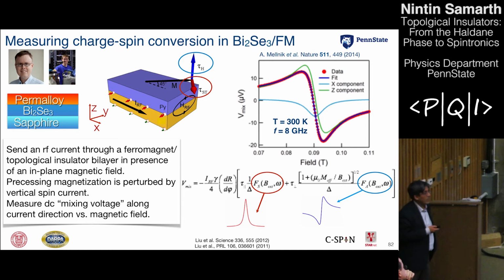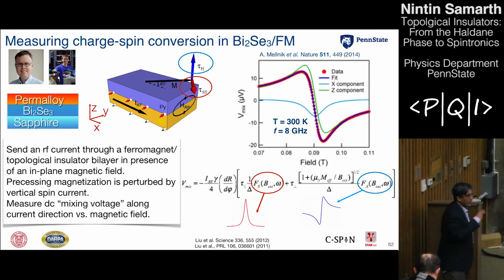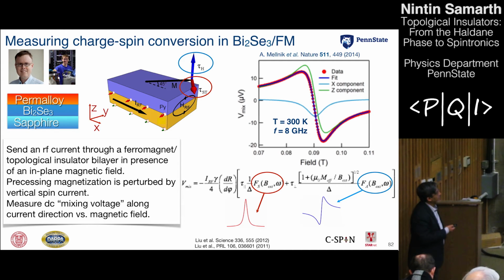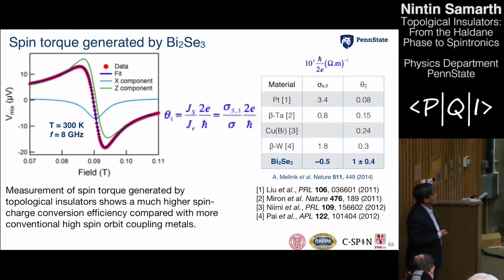And if you measure this mixing voltage, you get a curve which is a mixture of an antisymmetric and a symmetric signal. Now you can analyze this data, this mixing voltage data, and from it you can pull out this parameter theta. So you can effectively figure out by fitting data of this kind what is the spin to charge conversion efficiency. Okay? So I'm simplifying a complicated story into one slide, but basically the idea is that you just deconvolve this curve into two components, and then by using various fits and parameters, you can pull out what this parameter is.